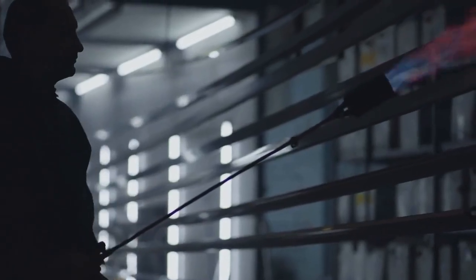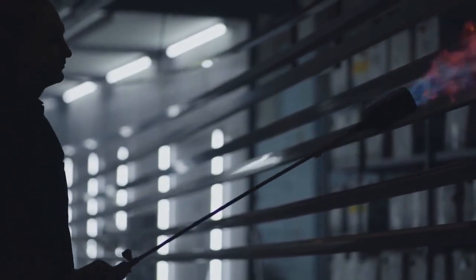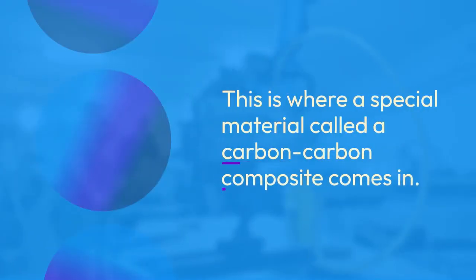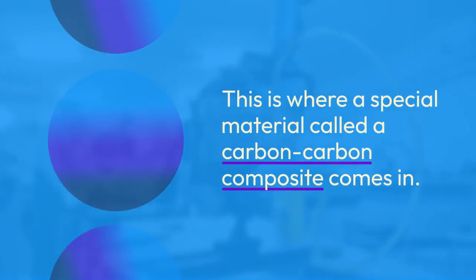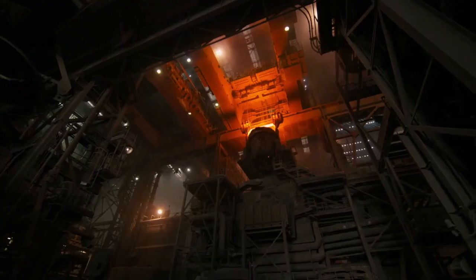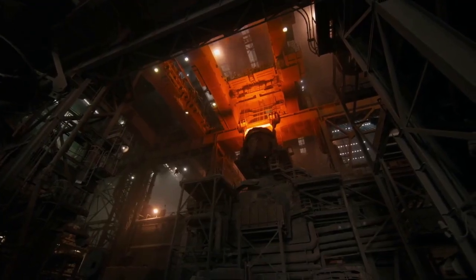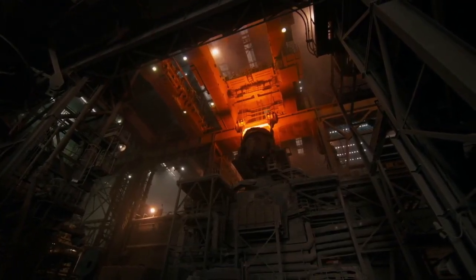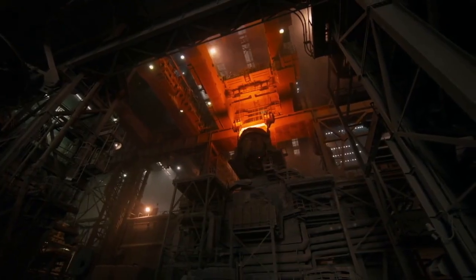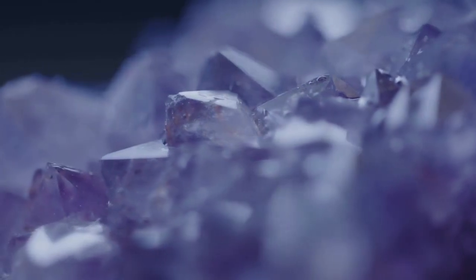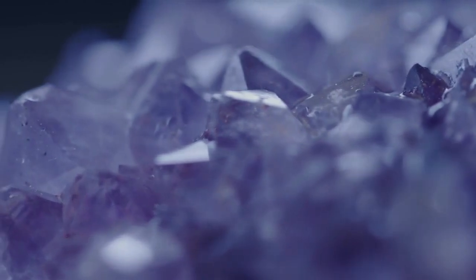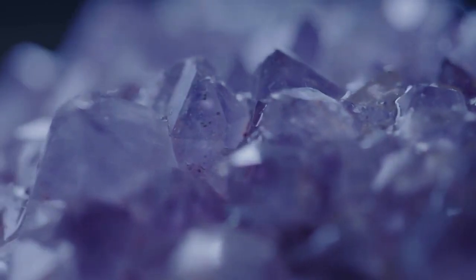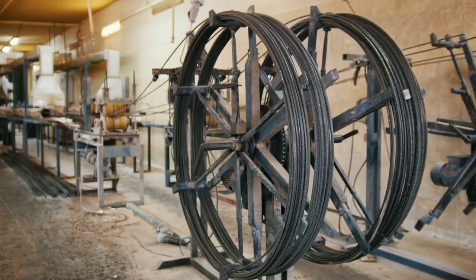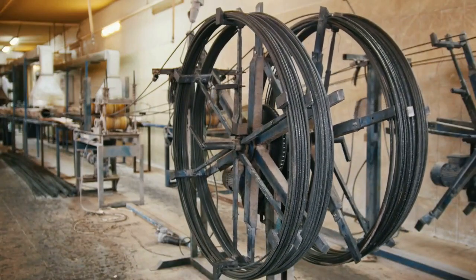But what if you need something that can handle truly insane temperatures? This is where a special material called a carbon-carbon composite comes in. To make this, you take a standard carbon fiber part and bake it in an oven without oxygen at extremely high temperatures. This process, called pyrolysis, burns away the original resin and leaves behind pure carbon. Now you have carbon fibers held in a matrix of pure carbon.